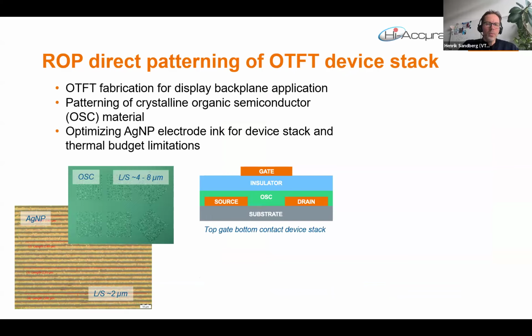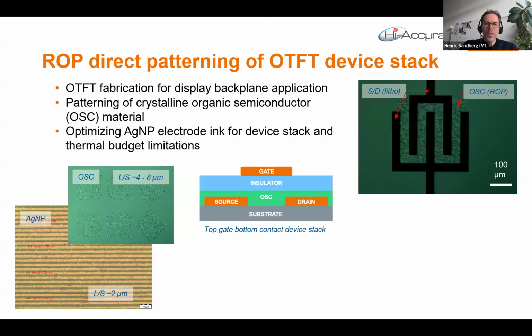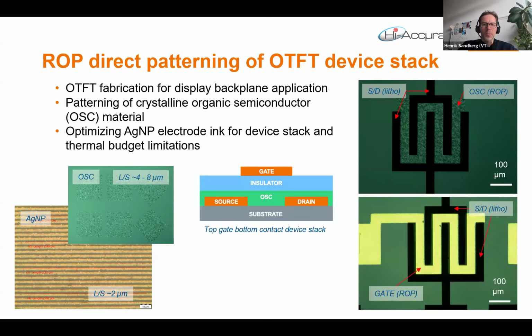And then also what is challenging is that we need to keep in mind that we are doing multi-layer structure. So we have to both think of the solubility in the solvent and the solvents for the various inks, and also the temperature or the thermal budget limitations. For the development phase, we also combined it with different lithographic steps to be able to really isolate the step or the manufacturing step which is being developed.